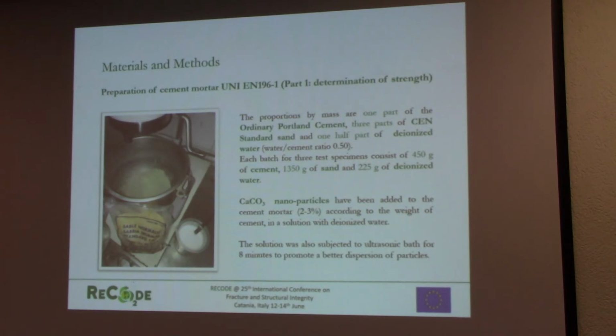The only thing is that the proportions by mass in this investigation are 1 part of ordinary Portland cement, 3 parts of standard sand, and 1/2 part of deionized water. In this case, we fix the water to cement ratio equal to 0.50, and the nanoparticles of calcium carbonate have been added to the cement mixture with 2 different percentages, 2% and 3% with respect to the weight of cement.